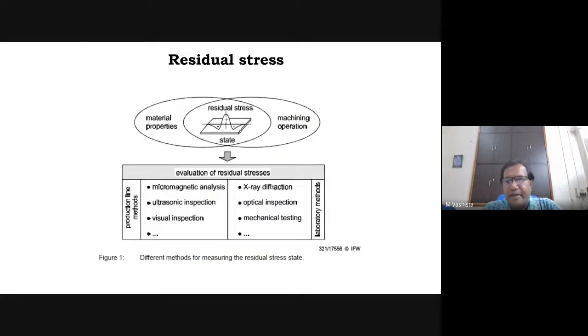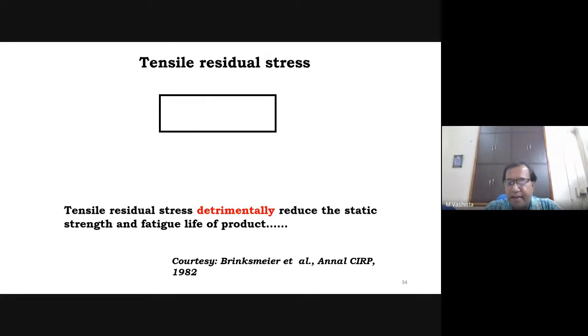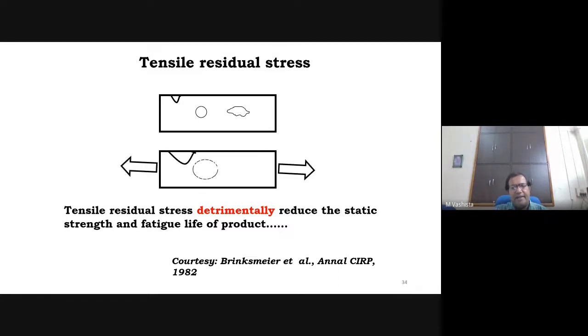For residual stress, remember the residual stress is very detrimental. We have seen that tensile residual stress should not be there. If tensile residual stress is there, it is detrimental. So we have to assess the residual stress. X-ray diffraction technique is there. Tensile residual stress is very much detrimental. Why? Because it will enlarge the irregularities present in the material like this.